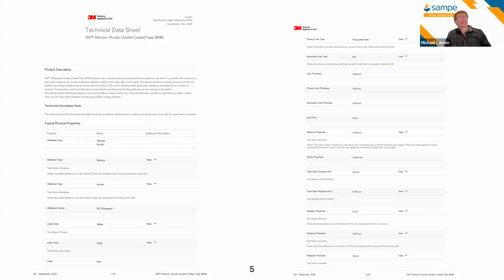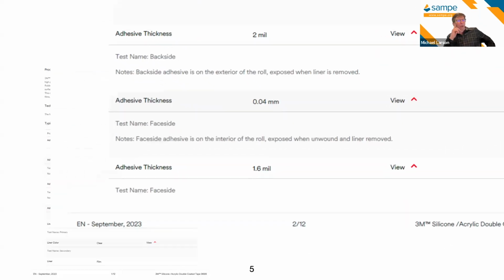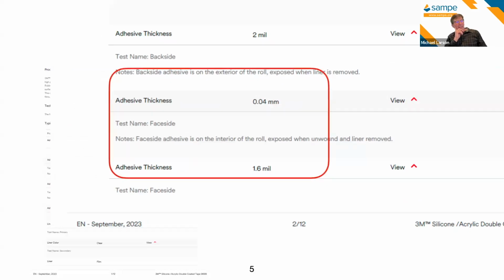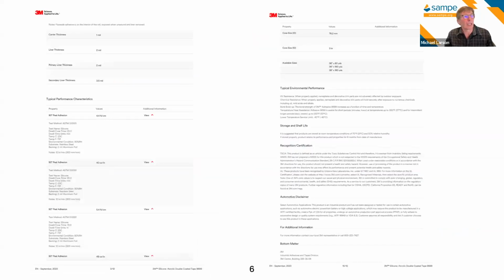If we look at the standard technical data sheet, just something I like to point out is the adhesive thickness for these tapes tends to be very small. We're talking 0.04 millimeters, 1.6 mil. And this turns out to be consequential when it comes to modeling these interfaces, because often we do trap this very complicated material in a very small zone compared to the environment that the failure is going to happen. And I think that works in our favor when we're thinking about a standard way of approaching our failure analysis, and certainly plays into the justification for using a fracture kind of approach for modeling these things.